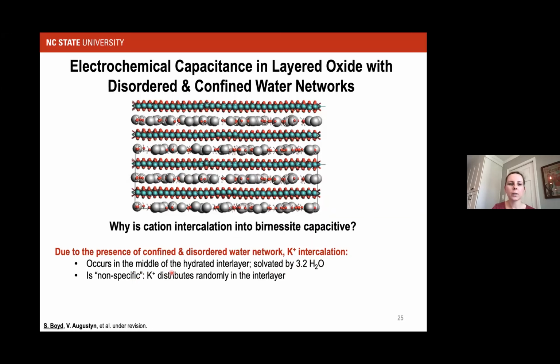The potassium has no specific site, that is, it wants to be distributed randomly in the interlayer. So that explains the potential dependence, as well as the fact that you have little structural change. So there's no first order phase transition. And the waters, again, we think play an important role in keeping the layers from rearranging when potassium leaves.